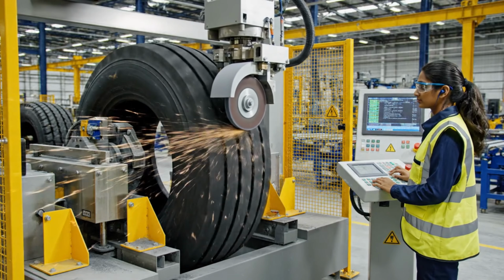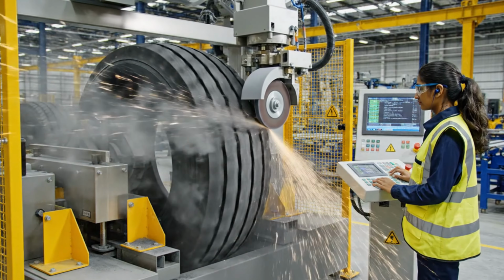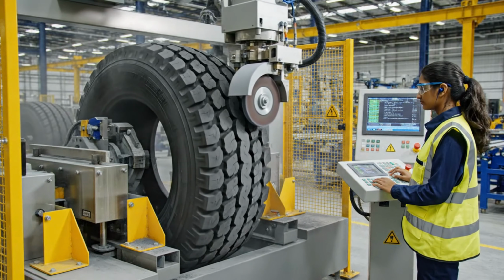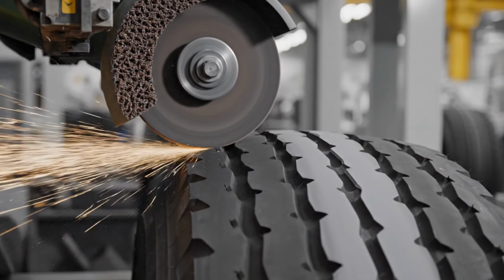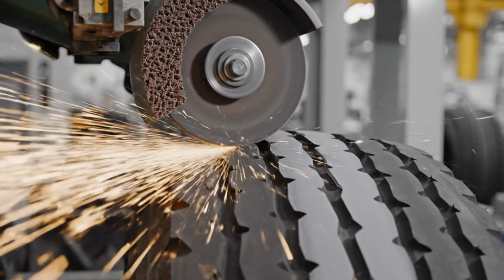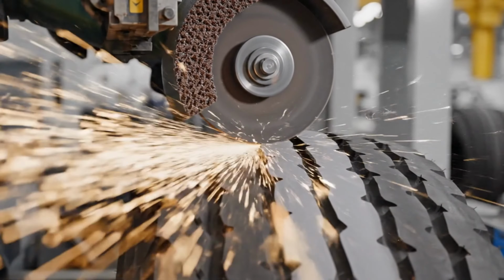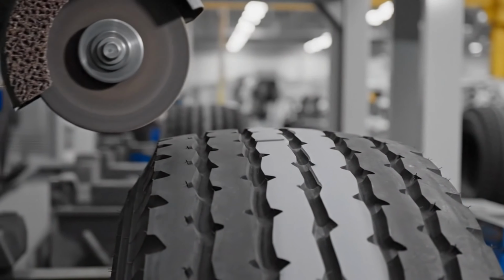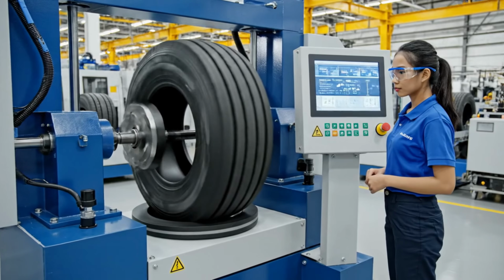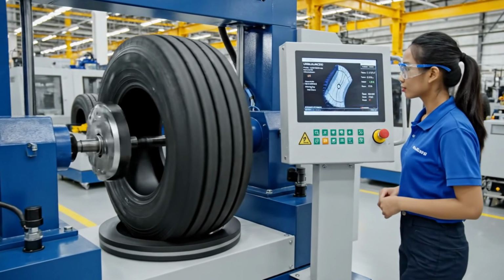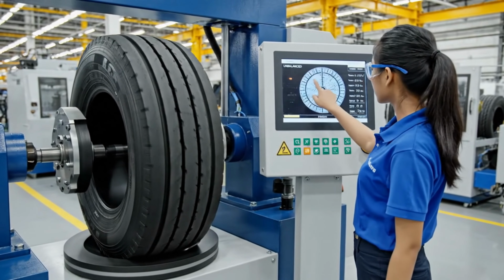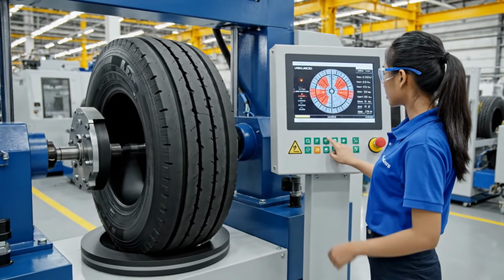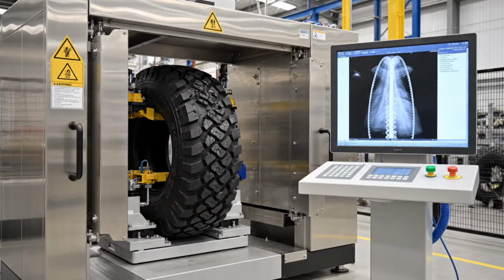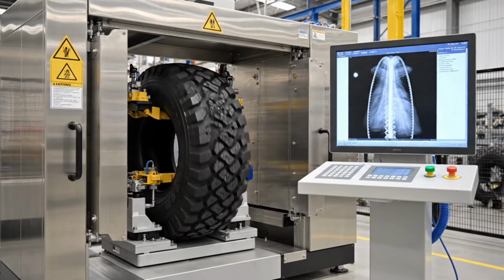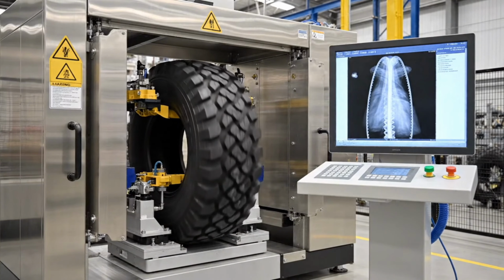Grinding stations can correct minor uniformity issues by removing small amounts of rubber. Precision grinding removes high spots that cause force variation. The amount removed is minimal but sufficient to bring uniformity within acceptable limits. Balance testing identifies weight imbalances that could cause vibration, while wheel weights can correct imbalance during mounting. X-ray inspection reveals internal structure invisible to surface examination.